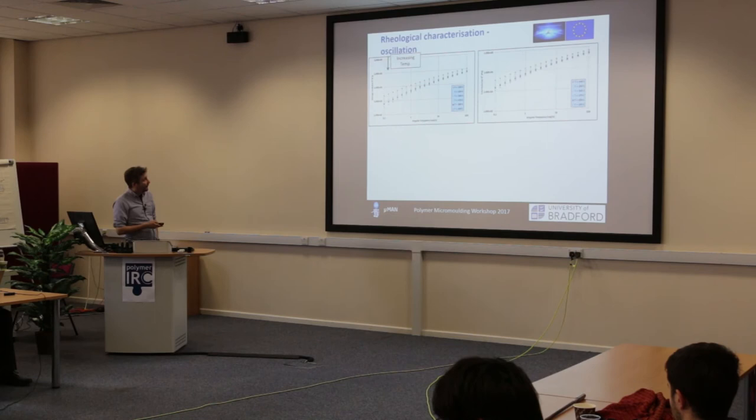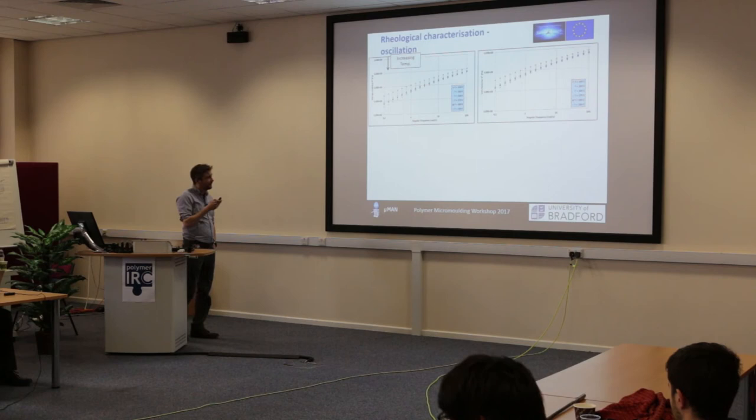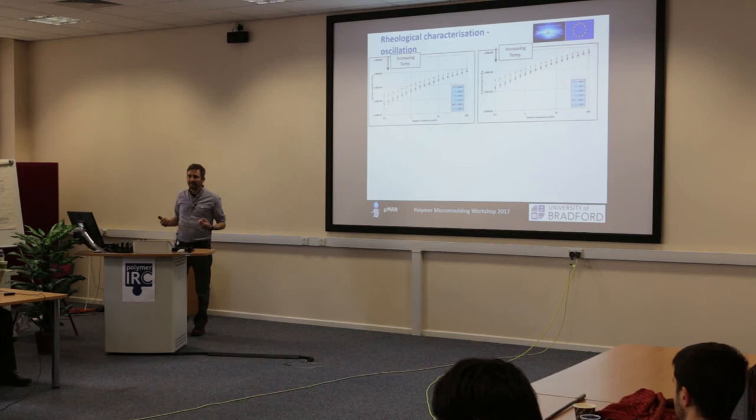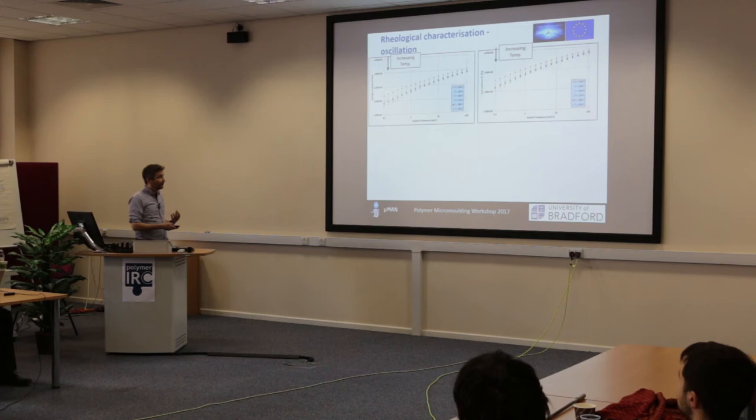Looking at the storage and loss moduli, they're a bit boring, but they give us additional information. So the storage modulus here, as I say, is to do with stored energy. So the energy that we push into the material by rotating or by oscillating. Okay, so this is our spring, basically. And this is our dashpot, okay? So this is our energy being dissipated by the material, by viscous damping, by taking energy out of the system. So that's what's known as loss moduli, okay?